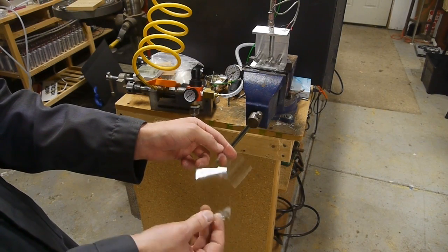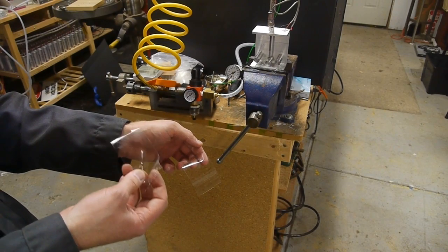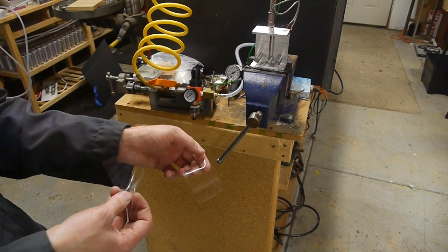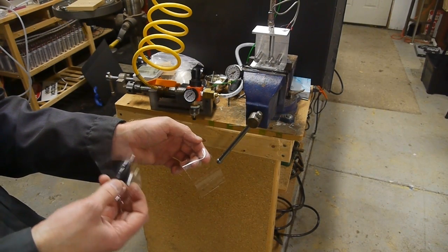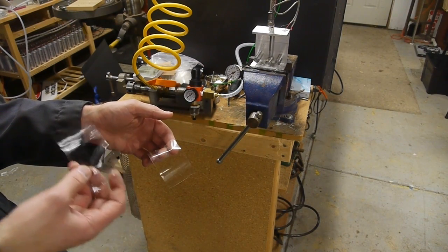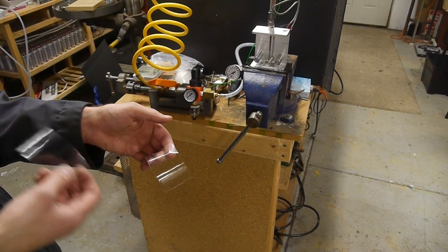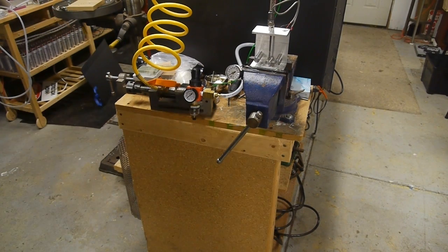You could say yeah but the material strength, the plastic of the tape, is still as strong as it always was, I just added that defect. But remember in materials like glass there are a huge number of defects in all pieces of glass that you'll encounter in the world. They're distributed throughout the material so it's actually the size and the number of the defects that determine how strong a piece of glass is. If we could somehow make a piece of glass that truly had no defects whatsoever it would be about a hundred times stronger or more than most glass that we encounter in the world.